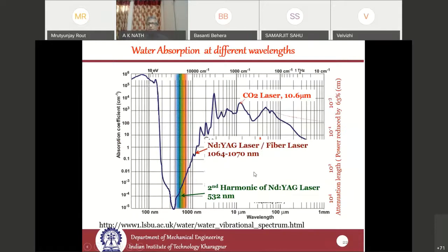If you see, the CO2 laser gets readily absorbed in water—it has a very high absorption coefficient. But compared to that, on this logarithmic graph, the Nd:YAG laser, fiber laser, and diode lasers, whose wavelength is in this range, have relatively low absorption. The second harmonic Nd:YAG laser has relatively very low absorption. So one can use, directly inside water, the Nd:YAG laser, fiber laser, or second harmonic of fiber laser/Nd:YAG laser, to do the processing.